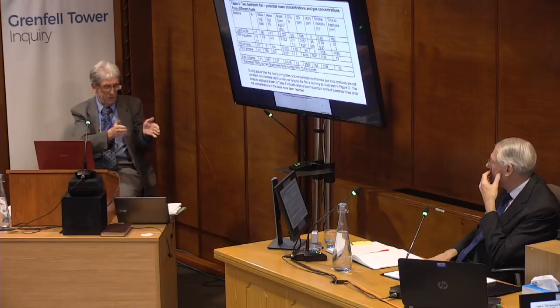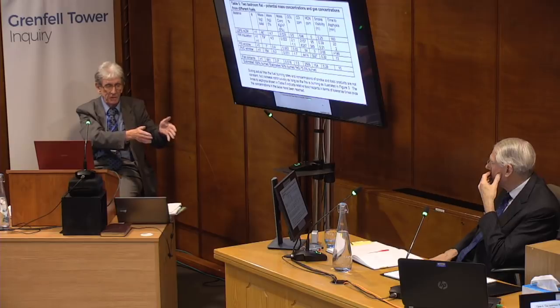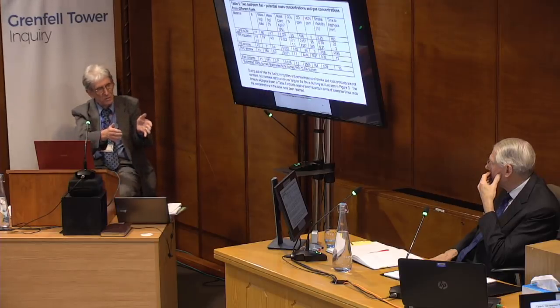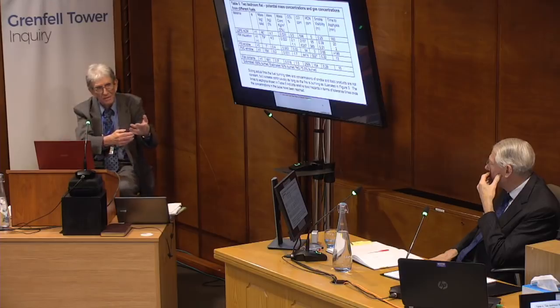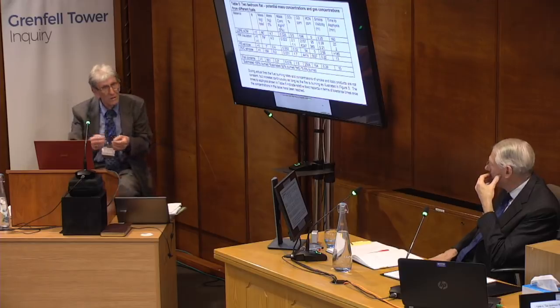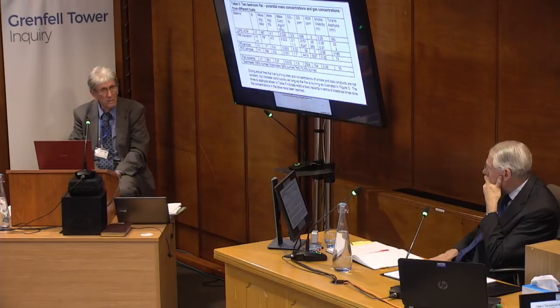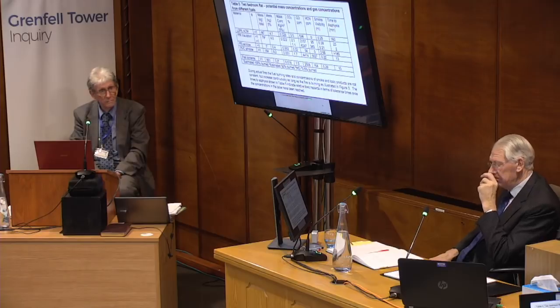So if, for example, you had a case where 50% had burned and gone, that's your 50%, and you had 50% left, of which 50% of the mass content had gone, leaving the charred bit, then you would end up with 75% of the total mass decomposed, which would be 25% more than I've assumed. So it can go in either direction. One of our plans is to look at the density of this charred material and estimate how much actually has gone from the specimens removed from the tower.